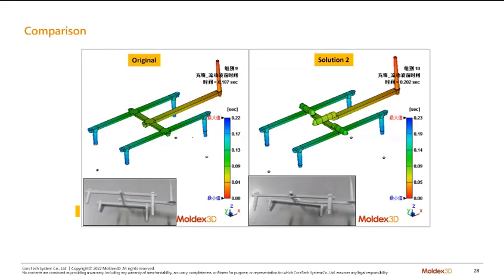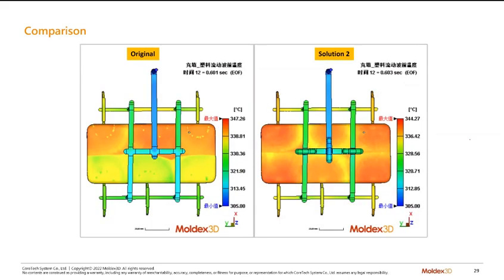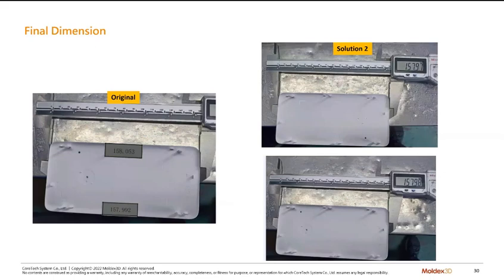And then they can check the melt front temperatures. You can see that it is more uniform in this solution 2. And the uniform temperature distribution will provide more uniform viscosity, and the pressure can transfer uniformly inside the cavities. So at the end, this one has a very good dimension, very similar dimensions on the top and bottom of the cavity. The difference is around 0.01 millimeters.